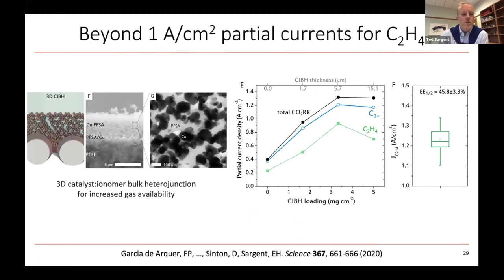for those of you who work in organic PV, I think of this as a little bit like a bulk heterojunction where you're mixing together the transport material, in this case, the CO2 transport material, and you're really intermixing it with, in our case, the catalyst, which of course also needs to be electrically conductive to get the reduction capacity there, to get the electrons there. So it's really an admixture of copper nanoparticles and the PFSA.